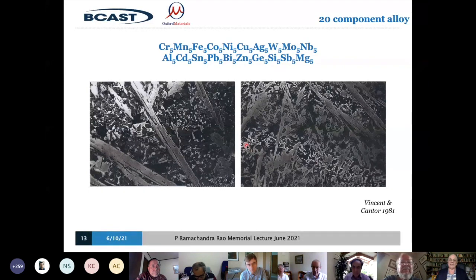It's a 20-component alloy. We didn't know where to start, so we just picked pretty much everything we could find that we could mix up together. 20 different components, chromium, manganese, iron, etc., etc., 5% of each. And it looked like this. We took some pictures of it in an optical microscope. We took some X-ray diffraction traces of it. It was fairly brittle. And we thought, it's a mess. It's a mess of a material. It's a complicated material. I'm not sure we'd learned very much, except that there are some very complicated materials, which you probably would have expected, I suppose.